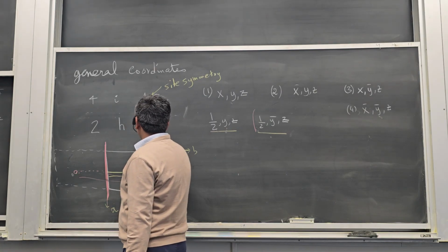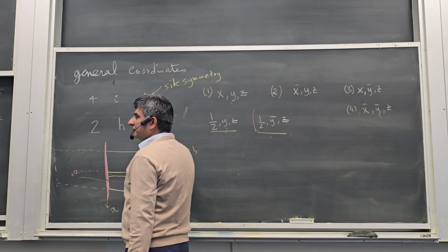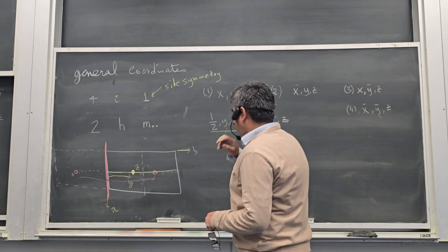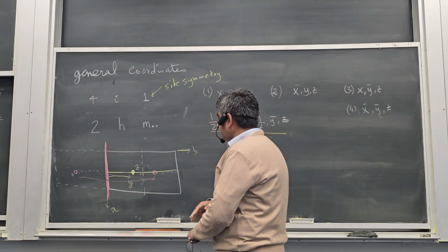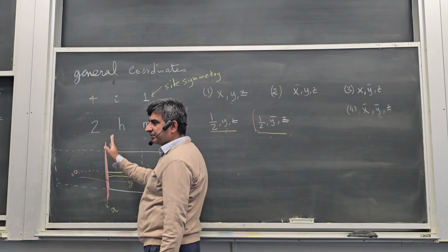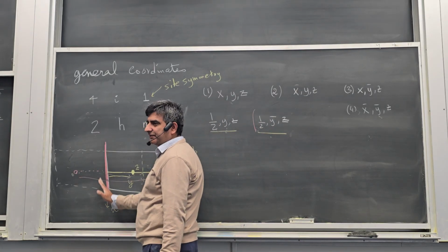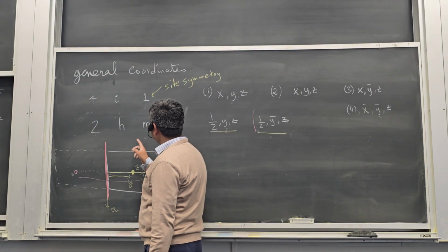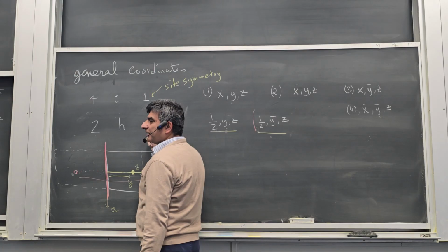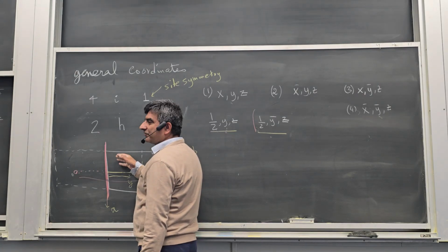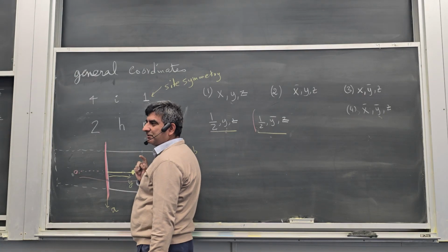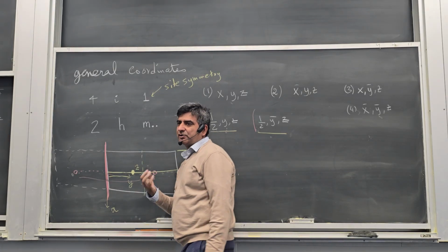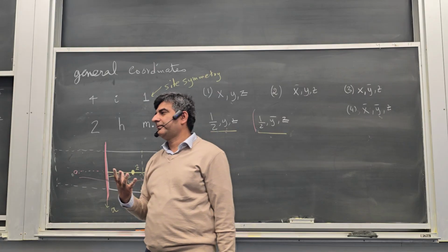Okay? And there is nothing on the other two directions. So a mirror plane along one direction, along the a direction, along the x direction. There is a mirror plane perpendicular to the x axis. That's why you put an m here. And then you don't need any additional symmetry elements along the y-axis or the z-axis. You put dots. So the site symmetry for this position, for the 2h position, is m dot dot.